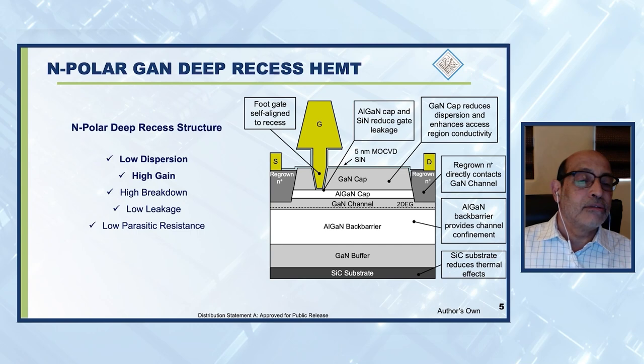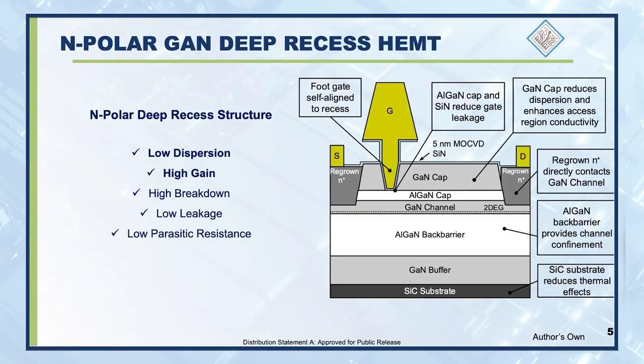Now you might say, oh, this is very simple. What's the big deal? Unfortunately, life is not so simple. And over the years, what we have developed at UC Santa Barbara is a device called the nitrogen polar gallium nitride deep recess HEMT. This device starts on a silicon carbide substrate. Silicon carbide substrate is very thermally conductive, so it reduces the thermal effects on the device.